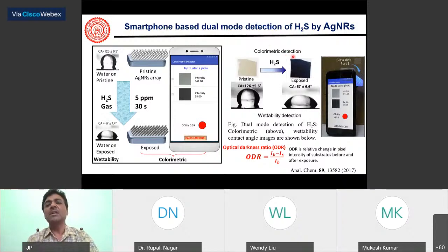So that was a very simple measurement, done using colorimetric measurements, just by detecting the color of the substrate. Also, because the material changes from silver metal to silver sulfide, the surface chemistry changes, so the wetting properties also changed. Just by observing the color change as well as the wetting property change, we were able to detect even a small amount of hydrogen sulfide gas coming out of the bacteria.